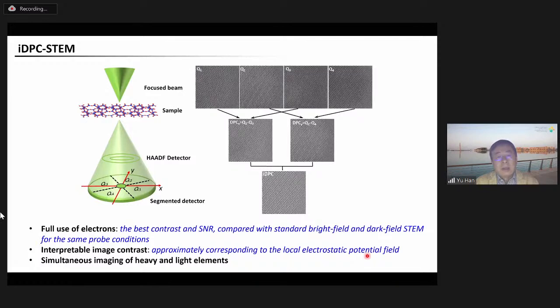iDPC-STEM has some unique properties. First, compared with the standard STEM modes, like bright field STEM, dark field STEM, or HAADF, high angle annular dark field STEM, iDPC-STEM gives the best contrast and the highest signal-to-noise ratio under the same probe conditions.